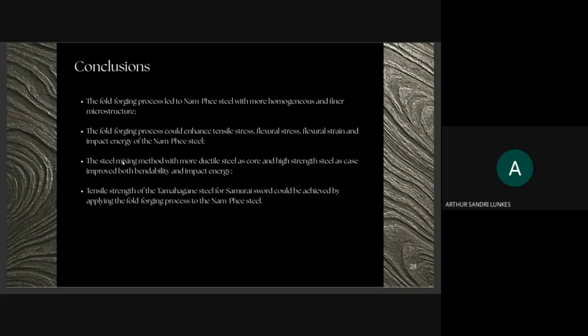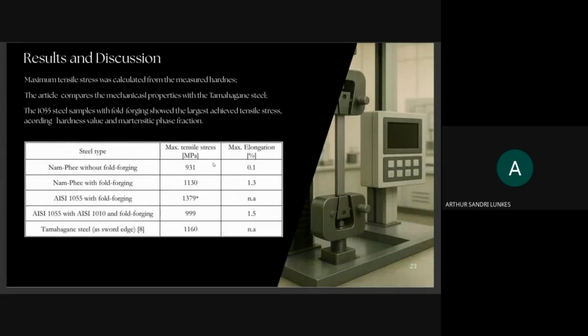For the bending steel, the method with more ductility improved the ductility of the steel and improved the strength of the steel too. It only obtained an improvement in the bending and impact energy for the mixing steel. The tensile strength of the Tamahagane steel of the samurai could be achieved by applying the fold forging process of the Nam-Phe steel. We could see this in the results of the tensile test on this graphic here. The Tamahagane steel maximum tensile stress is next to the Nam-Phe with fold forging process.